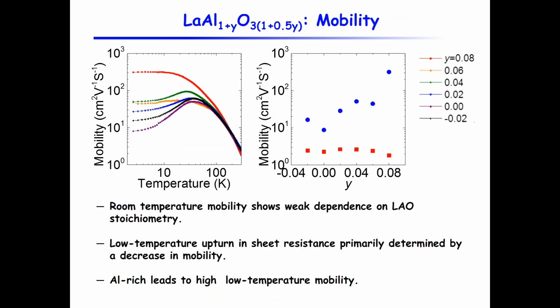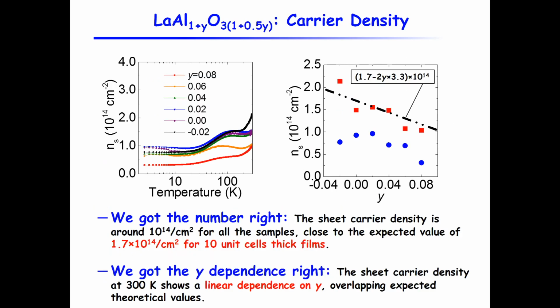And here is the mobility. These upturns are very much related to the mobility. The room temperature value doesn't really change much with stoichiometry, but the low temperature value does change. I think the mobility contributes mostly to this temperature dependence. And the carrier density.